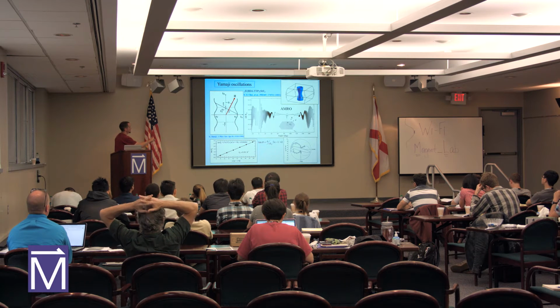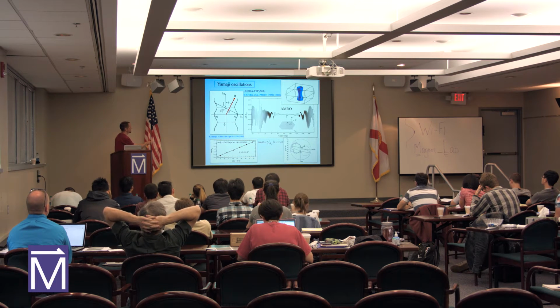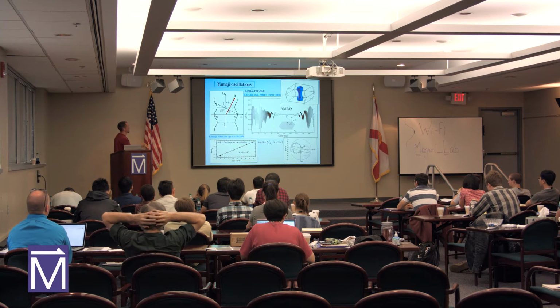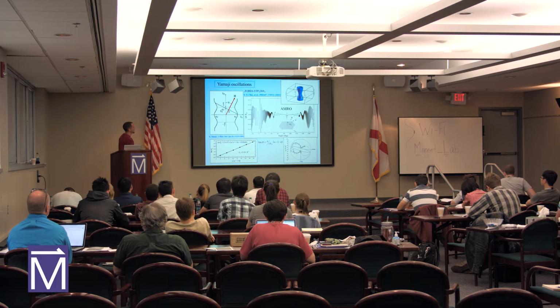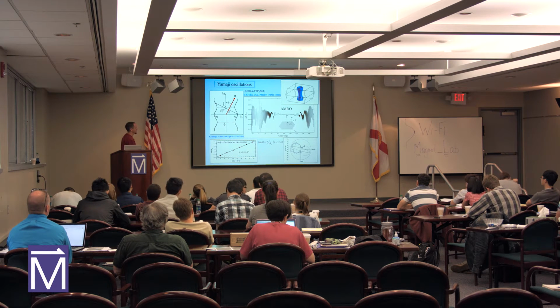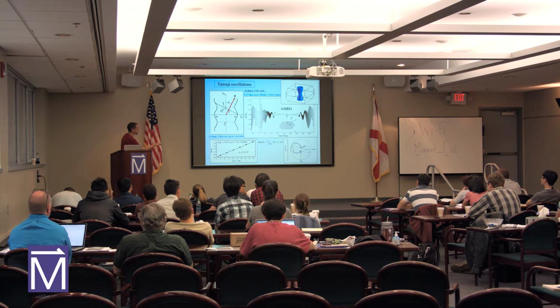But if you rotate the magnetic field away from this axis, you'll have points where the cross-section across the Fermi surface will have points where it's equal between the Fermi surface all the way along. What that means is instead of skinny necks and wide bellies, it's a uniform Fermi surface orbit for certain orientations. What this means as far as looking at the data is shown here. We still see these fast oscillations. These are just the Shubnikov-de Haas oscillations for measuring the sample, but these other oscillations here are what we call angle-dependent magnetoresistance oscillations.